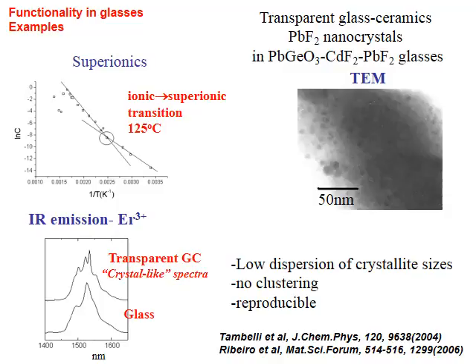Once doped with erbium ions, these ions will concentrate in the crystalline phase, and this is also very interesting. This figure shows erbium emission at the wavelength that is interesting for telecom purposes, that is, around 1.5 micron. Spectra obtained for the mother glass and for the transparent glass ceramics are different. In fact, the spectrum obtained for the glass ceramic closely resembles the spectrum obtained for the lead fluoride crystals doped with erbium, that is, a crystal-like spectrum is obtained for the transparent material that was obtained by conventional glass techniques.